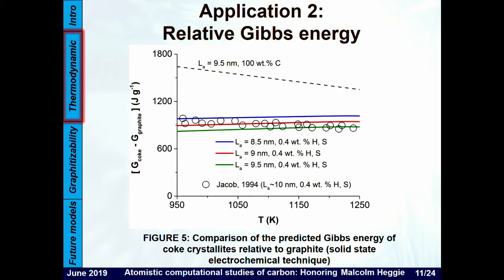You can do other applications for this basic Gibbs energy model. This is another comparison between the relative Gibbs energy of the coke crystallites and something that can be measured in an experimental apparatus using a solid-state electrochemical technique. As you can see, the results, more or less within the experimental error, are in agreement.